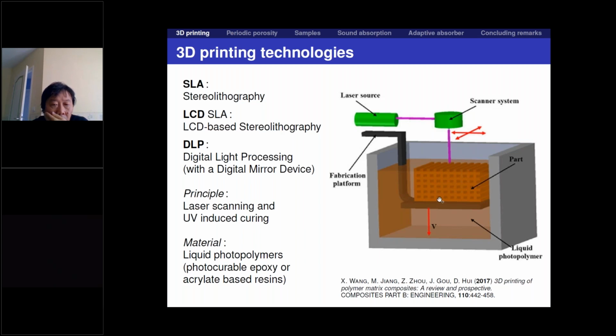After the process is finished, we need to take our object out from this resin unit. You see that we need much more material than only for the object. And then there's a second stage. We need to put this object under ultraviolet light to cure it. So there's some post-treatment involved here. But the advantage is that we have very fine prints with very high quality smooth surfaces, so much better quality than in the case of the FDM technology.